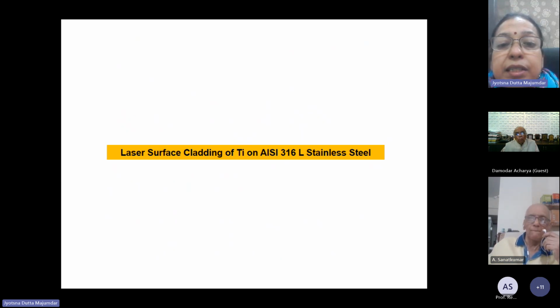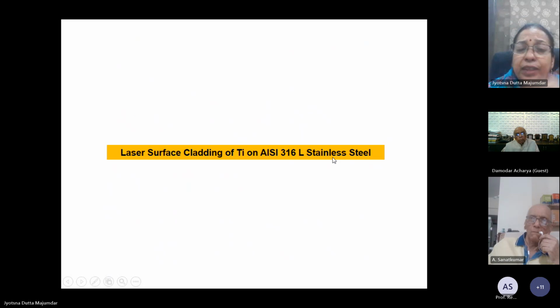on 316L stainless steel. AISI 316L stainless steel is much cheaper than Ti6Al4V or any titanium-based alloy. But the problems are nickel leaching and a higher corrosion rate. In addition to that, there is the stress shielding effect. Obviously, stress shielding is the core effect, which you cannot avoid by surface processing. But still, if you develop a very thick clad layer of titanium Ti6Al4V on AISI 316L stainless steel, then the corrosion problem can be addressed to a large extent.